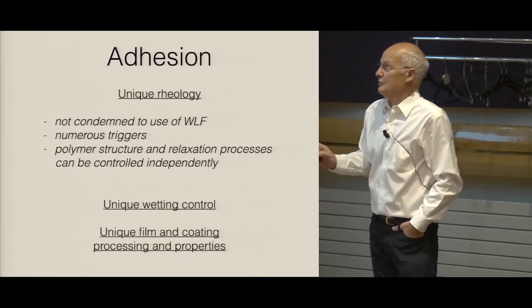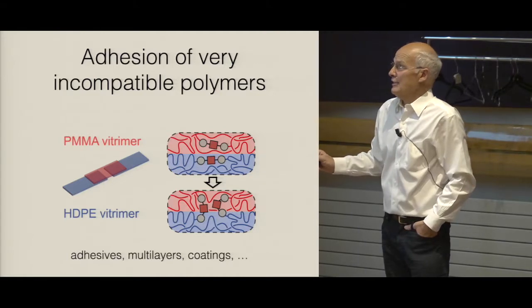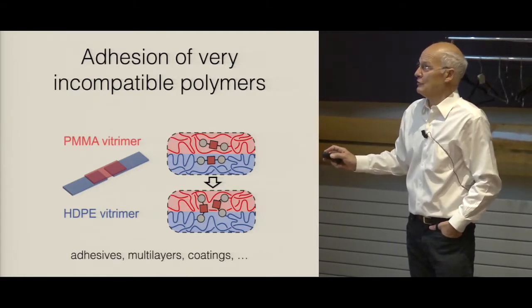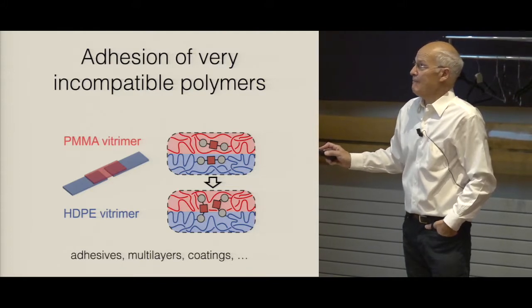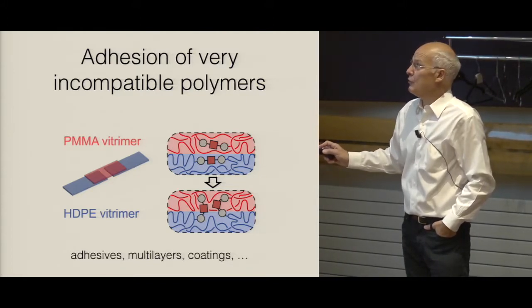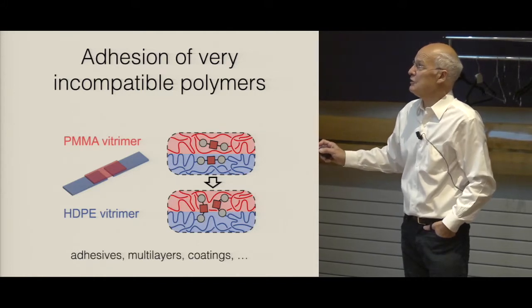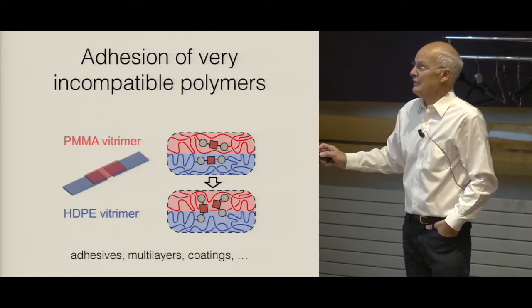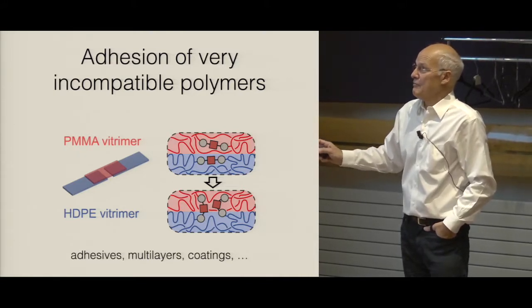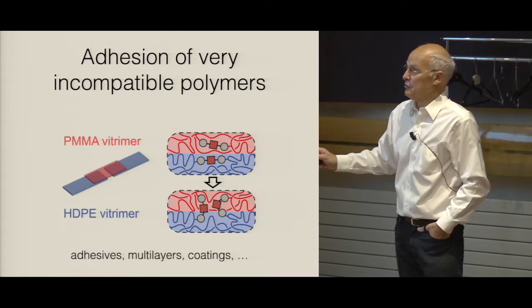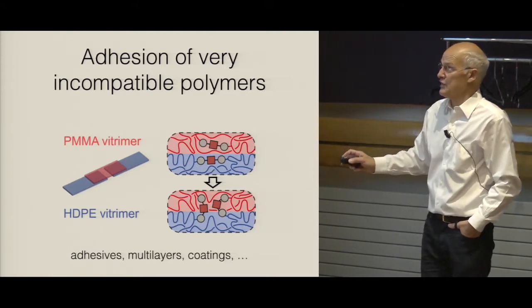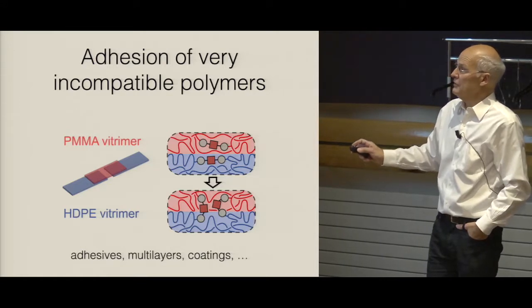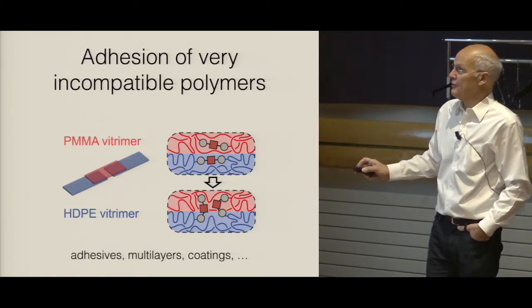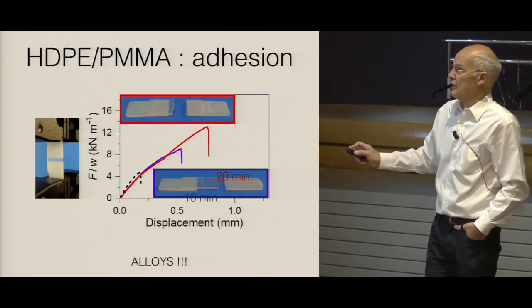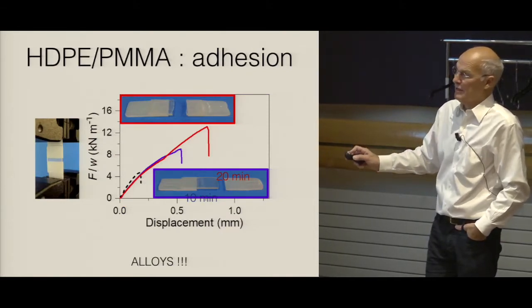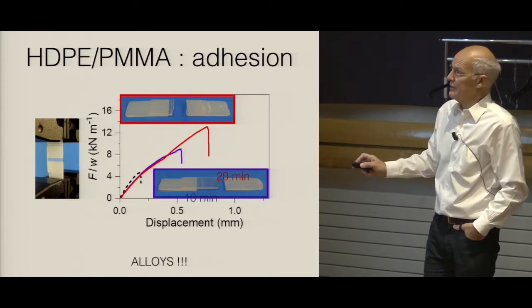Adhesion is again very interesting because we can control it, and in particular we can make adhesion of very incompatible polymers, because first we put polar groups which go into the surface, and then we have the reaction across the interface. So plexiglass, PMMA, and polyethylene are completely incompatible. There's absolutely no way to make adhesion of them. But if we introduce these boronic esters, we can get very strong adhesion. In some classical tests, we can even break the PMMA.